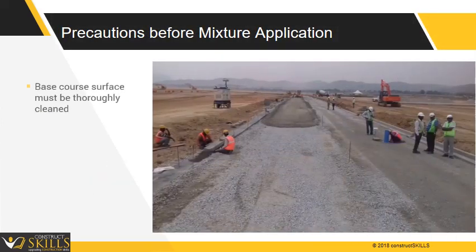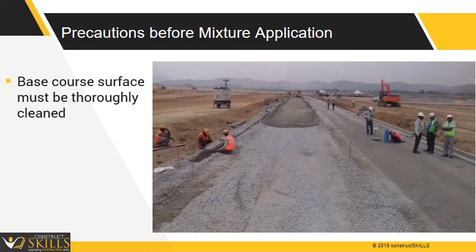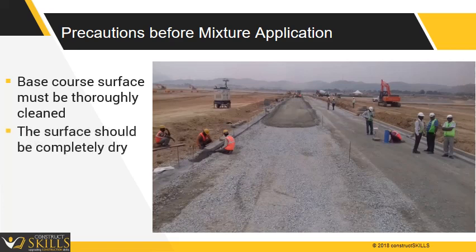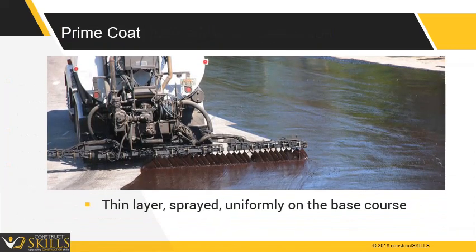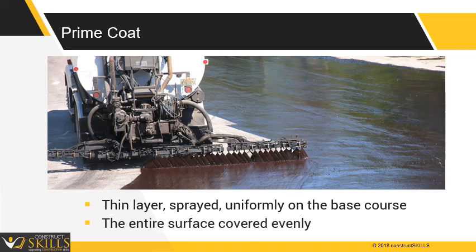The surface upon which the bitumen mix is to be placed must be thoroughly cleaned. Only after the base course layer has been dried for at least 24 hours in dry weather may preparation for laying a bituminous layer start, by applying the prime coat. The surface to be primed should be free from irregularities, potholes, and depressions. Prime coat is a thin layer sprayed uniformly on the road base course.